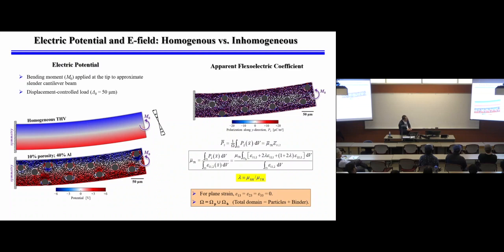But when you have microstructure, the fields are so heterogeneous. The particles and the voids make things very non-uniform. But the effective flexoelectric output, how much charge or electricity you can get out of the material from the same amount of deformation, is measured by this coefficient. Basically, it says that you have not only the regular shear component, you also have the other two components, the longitudinal strain, because for pure bending, you only have this strain. The longitudinal strain, the gradient in the vertical direction. And then Poisson's ratio says for this longitudinal strain, you have a gradient also. There is no shear here for pure bending. But because of the microstructure, you have shear, so you actually have a total of three contributions.